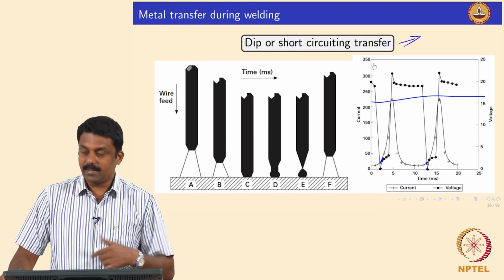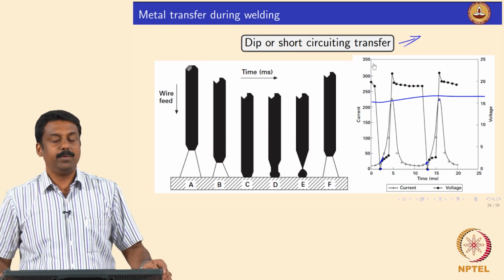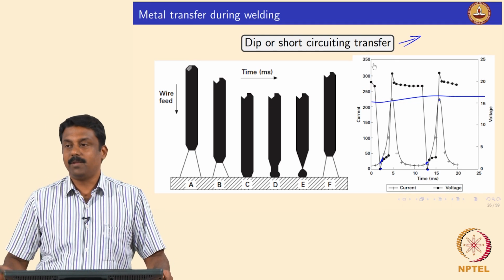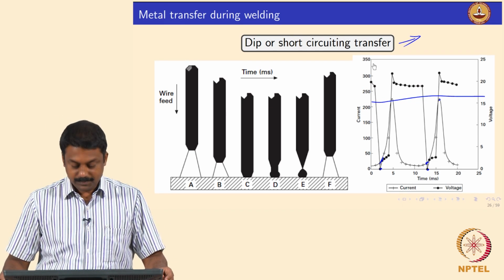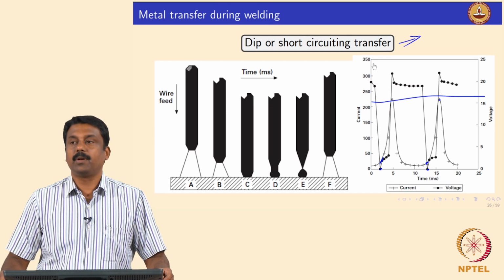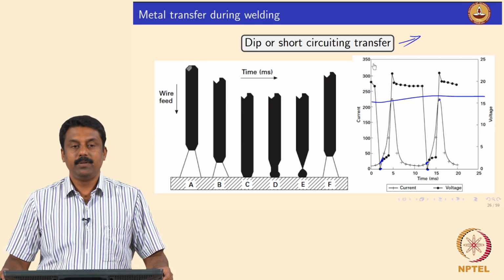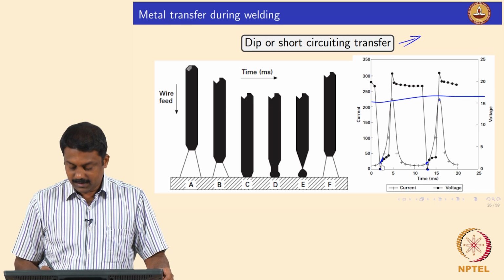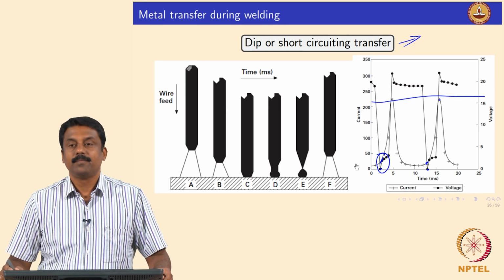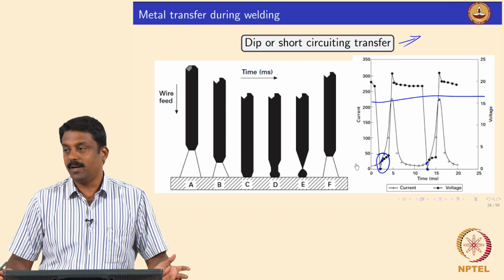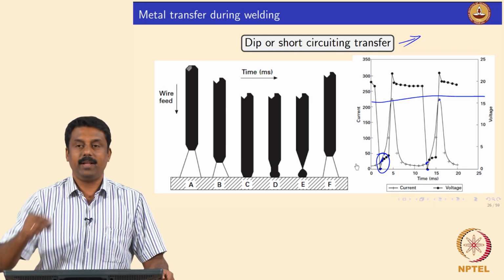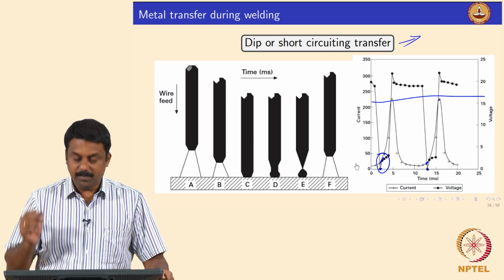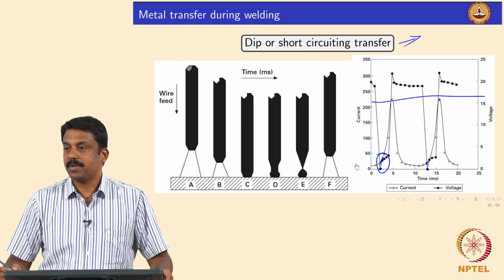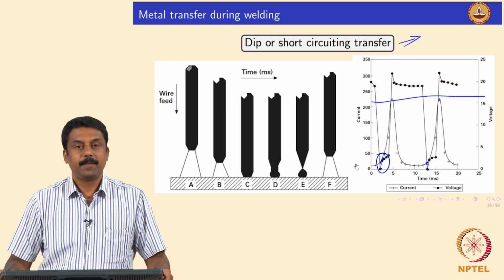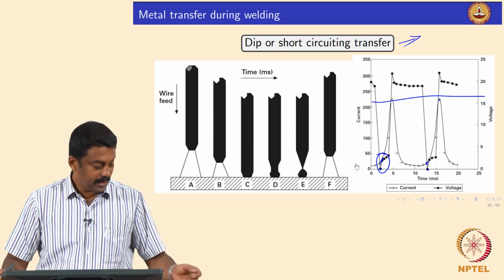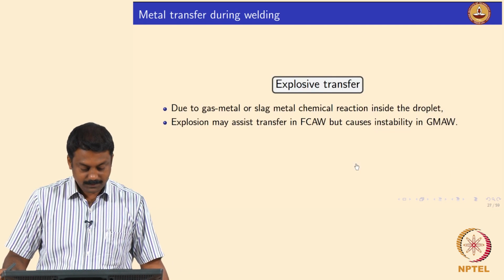We will see in some calculations, when you are looking at pulse GMAW, how short circuiting can be established after one time. It is clear, right, the short circuiting transfer, how you do it. The trickiest part here is controlling current and voltage. The voltage is controlled by itself because of this short circuiting. The moment short circuiting happens, current should be minimized to avoid explosion. Yes, it is clear. Okay, we will move on.